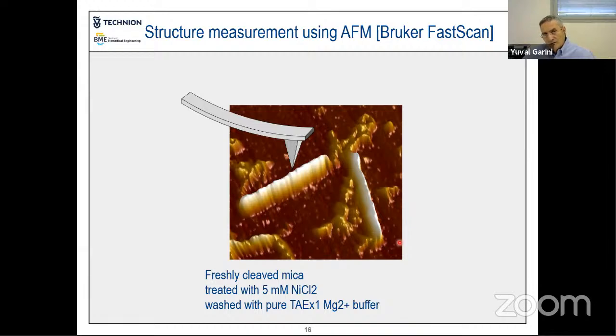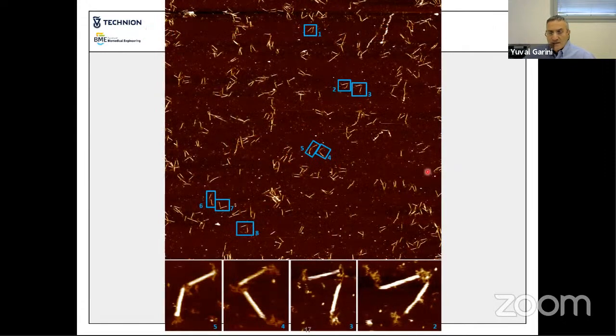Basically, we just drop a drop of the structure on a mica surface and let it adhere to the surface and then make the measurement. You can see many structures that were identified. However, some of them are too complex because you don't exactly know what's going on there. So we isolated and we only looked at those that are clearly isolated from all the others. You can see them here below.